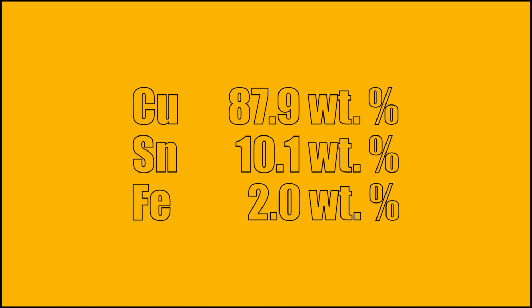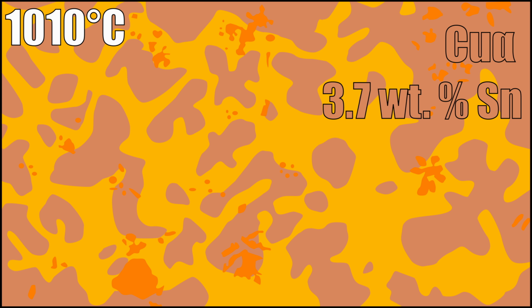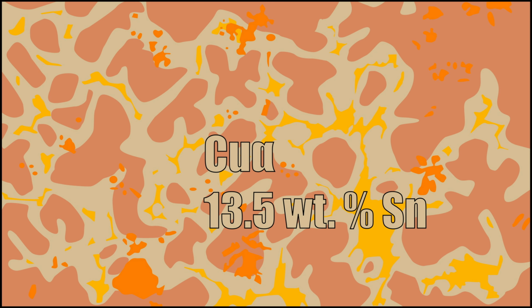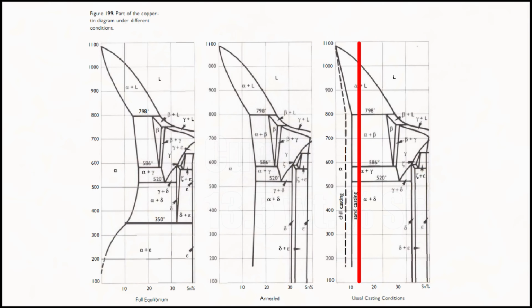It all started with molten metal of this composition, then segregation of iron, which is no longer miscible with the metal, then the start of crystallization, which gives us those low tin cores. Since there is no time for diffusion, the growing grains become enriched in tin, leaving the residual melt depleted in copper. I was fortunate enough to find this casting bronze diagram, and as you can see, much more happens.